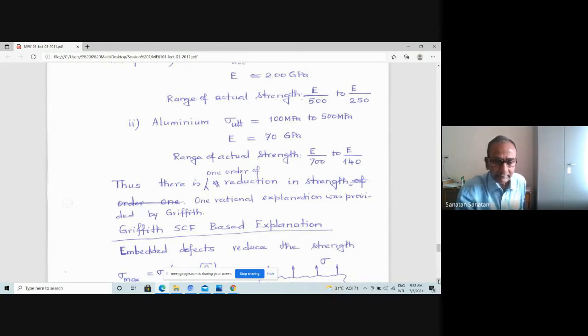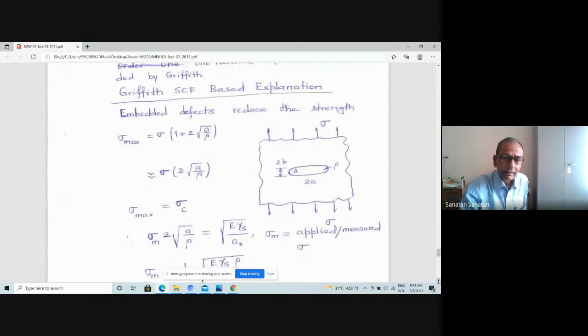It remained as a question, and scientists again started searching for the answer. The first answer was given by Griffith, who said that although we consider the material to be defect-free, in actual practice there could be defects in the material in the form of cracks, disjoints, and elliptical cutouts. That concept was brought in, and what they said is that although we apply sigma at the loading point, the stress which exists at the tip of the stress concentrator, a crack, is much higher. It is the stress concentration factor which amplifies the stress, and that is what acts and breaks the material at a much lower level of external load.